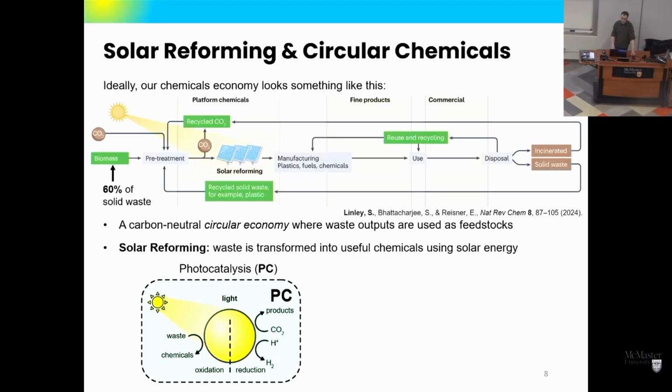This means we basically have some kind of semiconductor material. It absorbs light, and then it's usually coupled with some co-catalysts that will allow us to do specific oxidation and reduction reactions. And these usually happen on the same particle material, and there's no separation of our oxidation and reduction reactions beyond that. They're both happening on the surface of this single catalyst material.